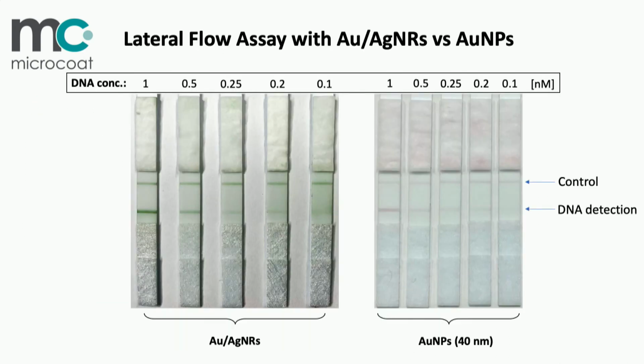So here's a first step where we did it with DNA, and you can already see, I mean, green is one of the most intense colors to the eye, so that also helps. But you can already see that even low concentrations of DNA were detected on this strip, whereas if you use the gold nanoparticles in comparison, it's very, very hard to see them. So we can already see an enhancement. And the hope is that later on we will get at least 10 times, hopefully 100 times signal enhancement for these strips for detection of viruses or cardiovascular disease markers.